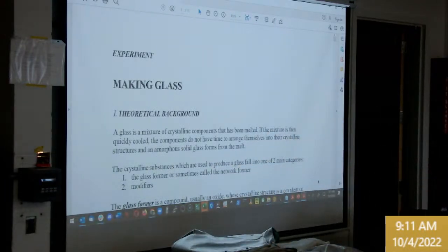But first I want to talk about some of the relevant background for what's happening in that crucible. So last week we chose a recipe. We put in a glass former, which is silica. We put in a flux, sodium carbonate. We put in a flux stabilizer, calcium carbonate. Some of you put in some aluminum oxide, which is a stabilizer. Some of you put in Gerstley borate, which is a melting agent, or essentially a flux, but it's kind of like riding the fence between a lower melt temp glass former and a flux. But that should make the viscosity go down in theory.